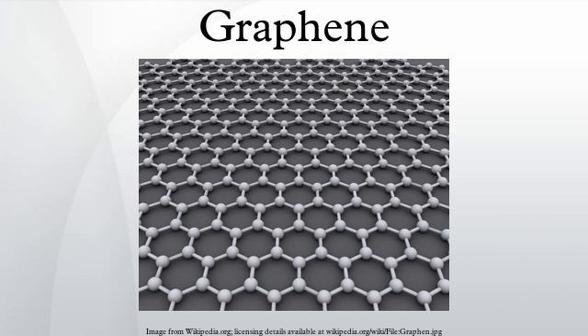Optical. Graphene's unique optical properties produce an unexpectedly high opacity for an atomic monolayer in vacuum, absorbing πα, about 2.3%, of white light, where α is the fine structure constant. This is a consequence of the unusual low-energy electronic structure of monolayer graphene that features electron and hole conical bands meeting each other at the Dirac point, which is qualitatively different from more common quadratic massive bands.